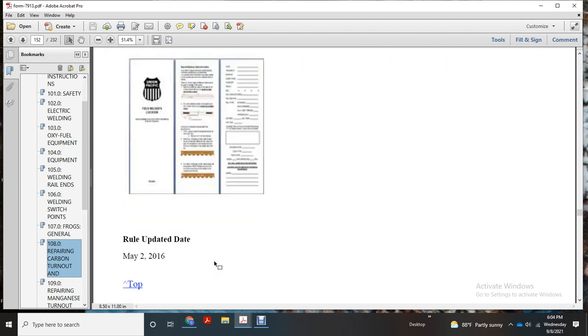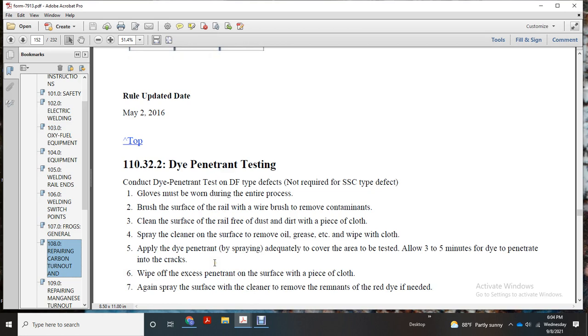110.32.2. Dye penetrant testing. Conduct a dye penetration test with the DF type defects, not required with the SSC type defect. Gloves must be worn during the entire process. Brush the surface of the rail with a wire brush. Remove contaminants. Clean the surface of the rail free of dust and dirt. Use a piece of cloth. Spray cleaner over the surface.